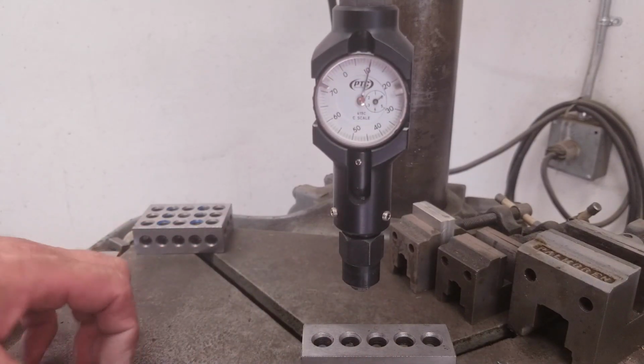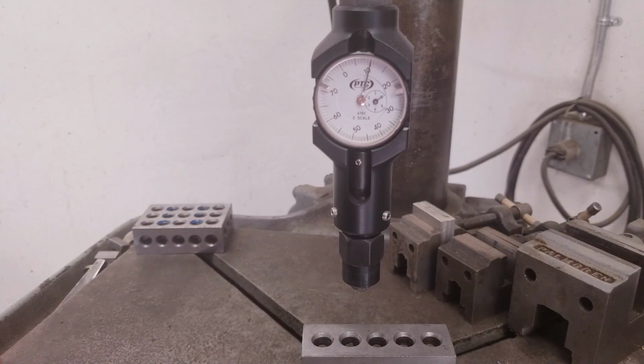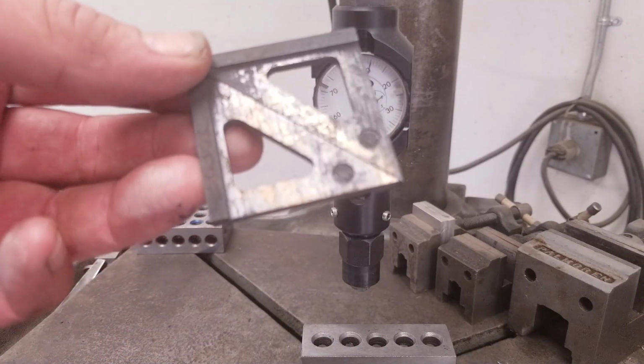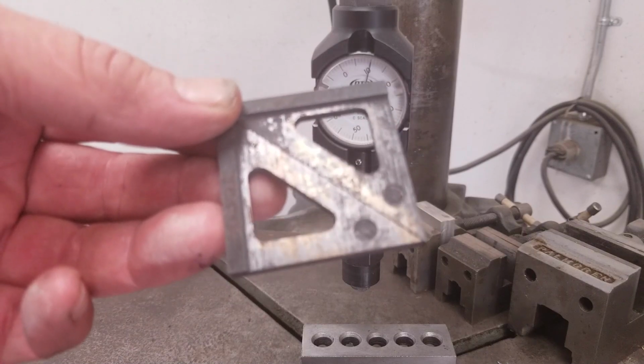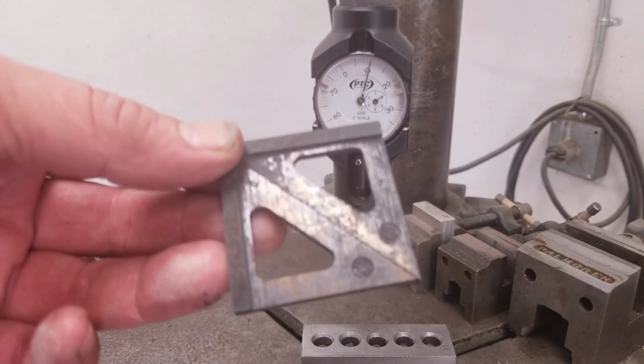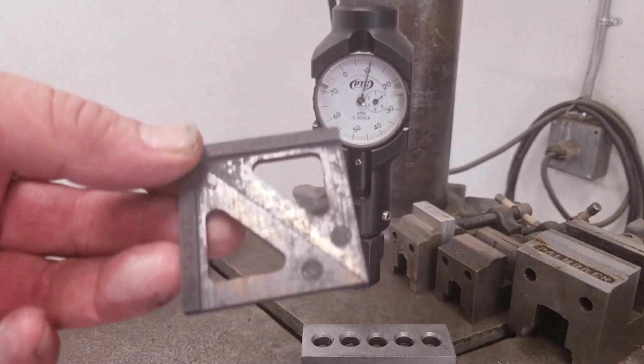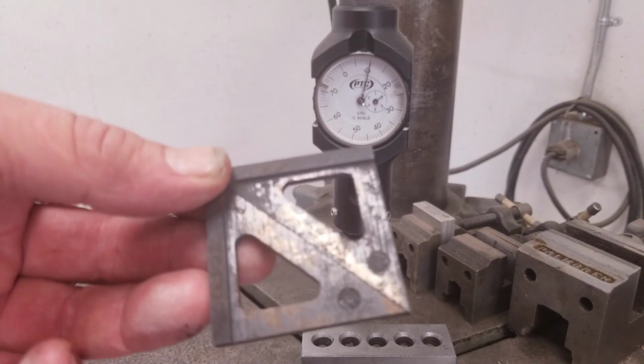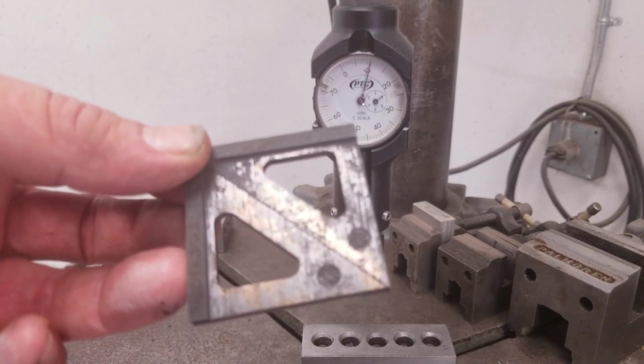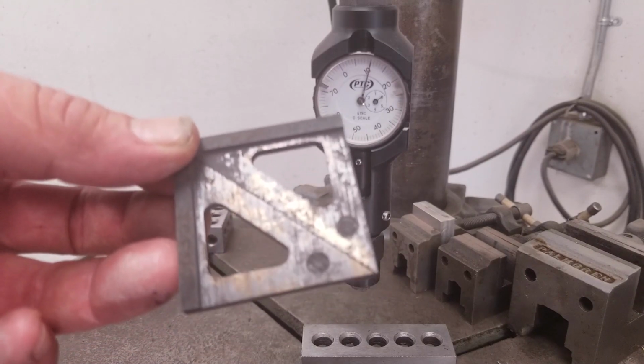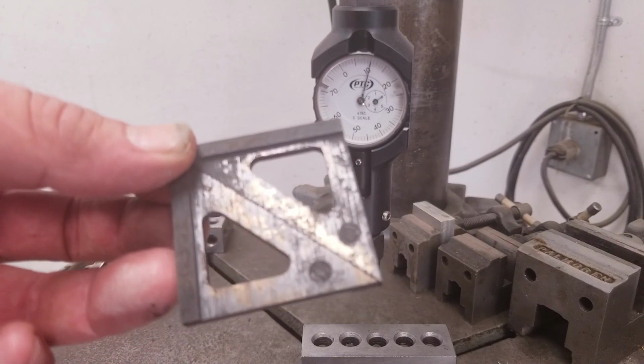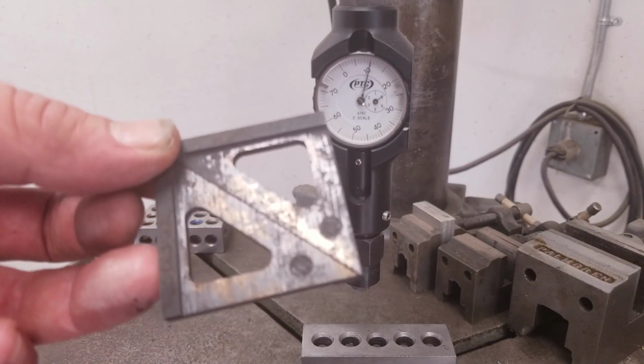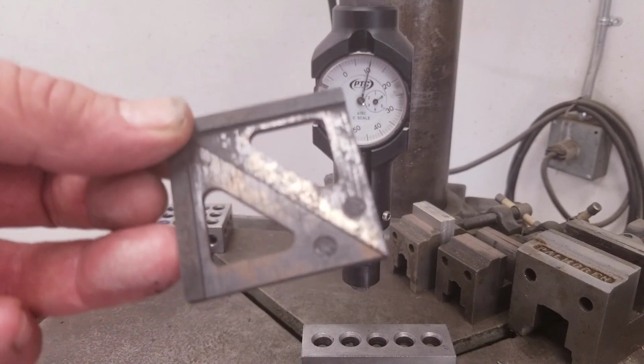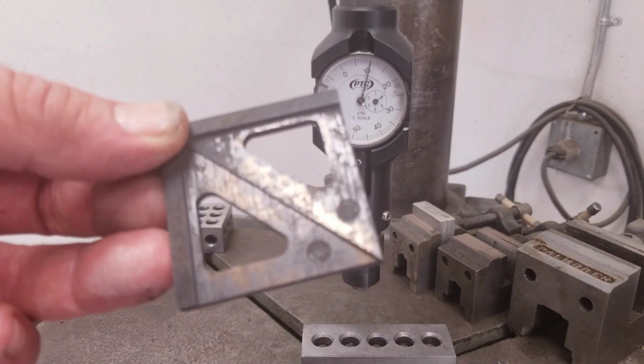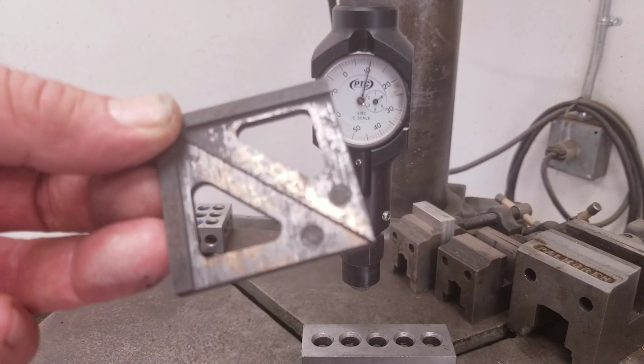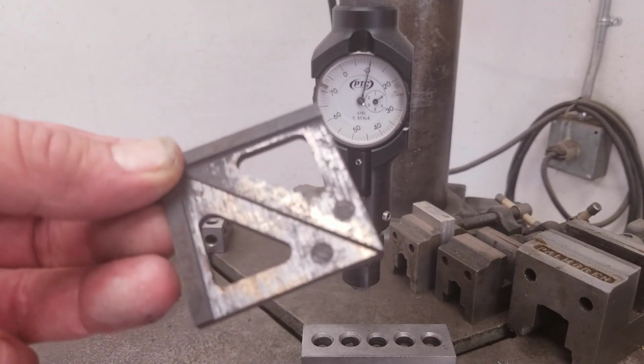You start seeing more consistent numbers after you temper them, because tempering kind of relaxes the part. All your numbers start coming in. When you're heating, quenching, and just dropping parts in oil, any little bit of air moving over the part makes a difference. The temperature of oil makes a difference. Everything matters when you're doing the heat treat process. So you get numbers kind of all over the place. When they stabilize is after you temper them. That's when your numbers really start to come in and you start getting nice even numbers. So that's how we accomplish that.